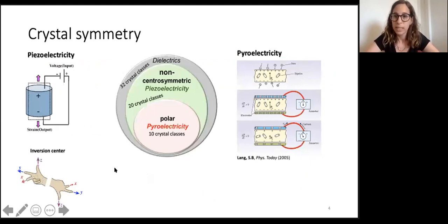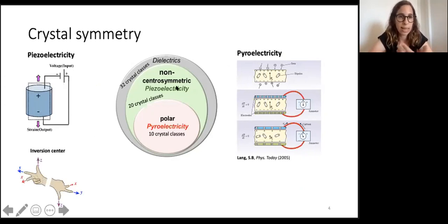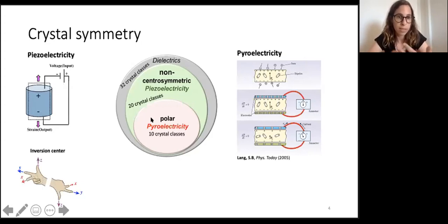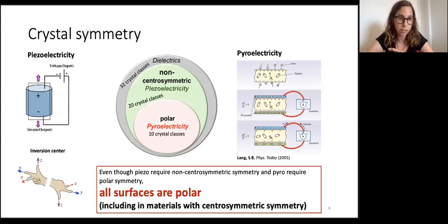Crystal symmetry defines a large variety of material properties, and pyroelectricity and piezoelectricity are among them. Piezoelectricity is a property of dielectrics lacking inversion symmetry, while pyroelectricity requires a polar crystallographic direction. Therefore, all pyroelectric materials are also piezoelectric but not necessarily vice versa. Importantly, all surfaces are polar — including in materials with centrosymmetric symmetry — so even centrosymmetric crystals can show surface effects.